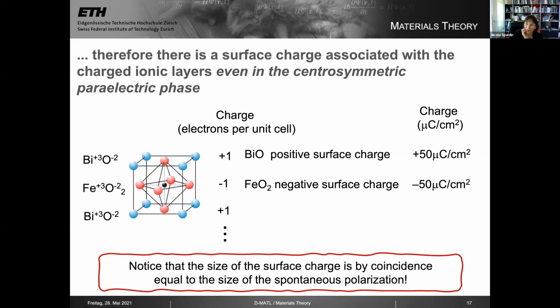And if you remember back to when we first looked at the polarization in bismuth ferrite, the spontaneous polarization in this 001 direction, the polarization that comes from the ferroelectricity when the bismuth ions displace relative to the rest of the unit cell, that also had the value of 50 microcoulombs per square centimeter, right? I want to emphasize this is completely coincidence. Bismuth ferrite is the only material I know where this happens. It's completely an accident, but it's going to lead us to some very interesting, I don't know whether to call it physics or chemistry, very interesting kind of physical chemistry as an outcome.